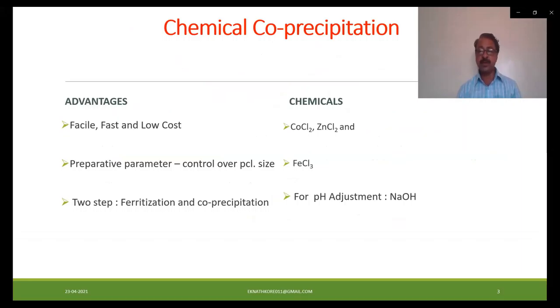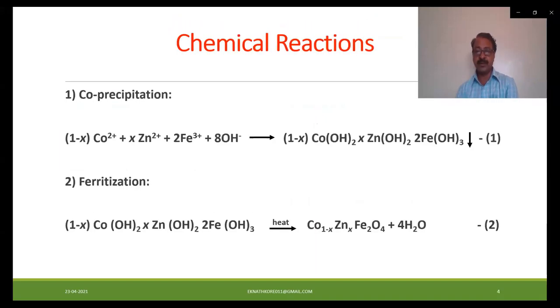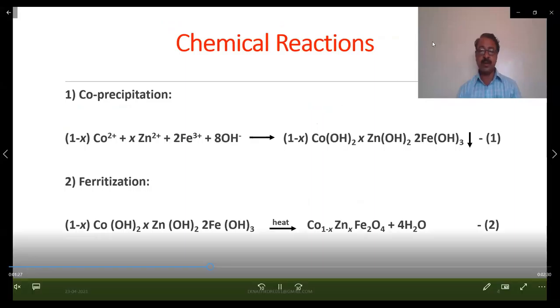To synthesize, equimolar solutions of CoCl2, ZnCl2, and FeCl3 were mixed in their stoichiometric ratio. To this, NaOH solution was added for alkaline medium. Further, the solution was heated and homogenized. Different preparatory parameters were optimized: temperature 70 degrees Celsius, pH 10, time of study half an hour.